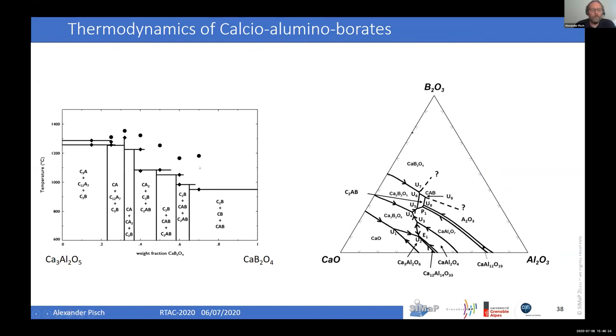So we also did some experimental work in order to determine the liquidus relations. And it's clear, you can see the low temperature compound doesn't exist because it's not stable at high temperature. But with these two ternary compounds, they have some associated reactions. And now everything is there to make a full CALPHAD assessment of these systems, if somebody is interested in it.